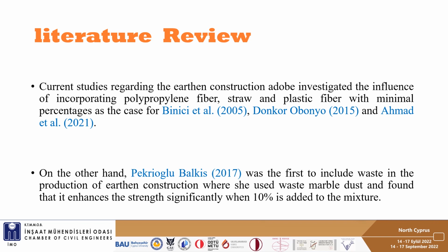On the other hand, Pekrioglu Balkis in 2017 was the first to include waste in the production of earthen construction, where she used waste marble dust and found that it enhanced the strength significantly when 10% is added to the mixture.